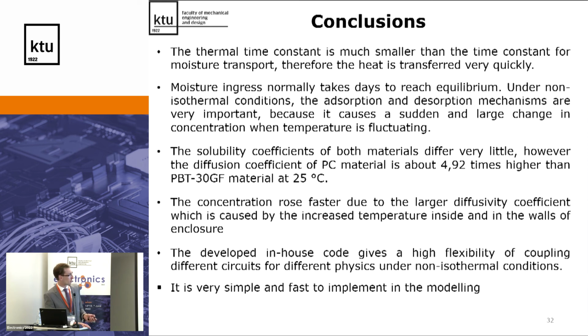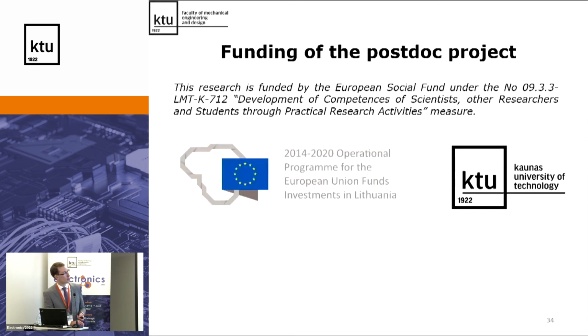And of course, the code shows quite good flexibility of coupling different circuits for different physics. And it's very simple and fast to implement in the model. And one more thing, the diffusion coefficient of polycarbonate material is about 5 times higher than the PBT material at this temperature. The project is funded by the European Social Fund.